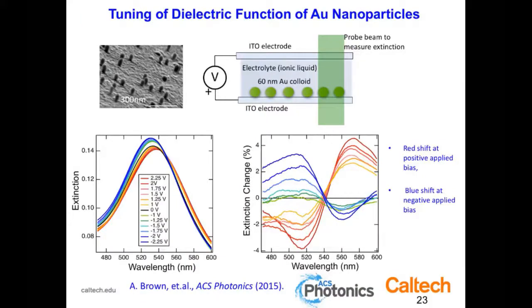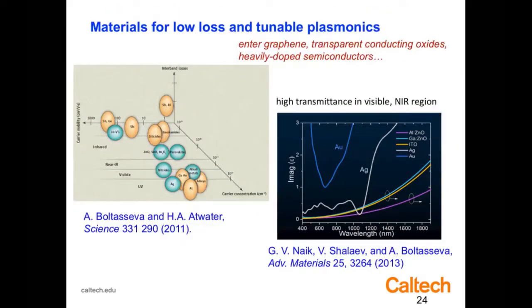OK. So we need to go to some slightly different materials. And we're going to go to materials that have slightly lower electron densities. The thing is, the external electric field is so efficiently screened in a good metal by the high density of the electron gas, we need to lower the electron density. If we go all the way to a semiconductor, now we lose the negative permittivity that makes plasmonic structures special. So we're going to go to materials that have intermediate electron densities. Some of these are intermetallics, like silicides, conducting oxides, graphene, many of the two-dimensional materials that have carrier densities intermediate between those of metals and semiconductors.